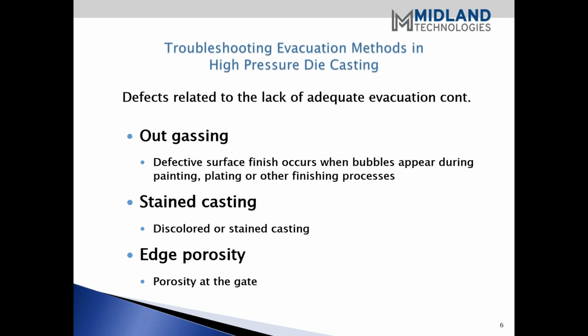And by evacuating the cavity properly, of course, we can minimize that condition by either using adequate venting or vacuum. Stained castings, of course, are discolorations that occur from the actual contact of the metal with constituents in the cavity itself, such as primarily spray, or can also be caused by the lubricants in the shot sleeve. And when the metal comes in contact, of course, it creates a carbon, and that's what creates the discoloration. Generally, you can't get that out of a casting unless you use a vacuum to remove it. There are other ways of minimizing the amount of spray and so forth that you address that problem too.